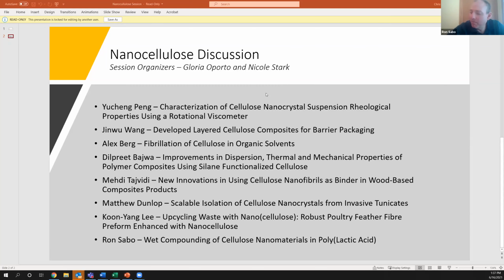You're on. So can you talk a little bit about the dewatering or press times and how these compare to traditional fiberboard processing, and maybe what you can do to improve that dewatering process? Yeah, the dewatering that we first started with was actually one-time dewatering. In one-time dewatering, we get to about 50% solids of our system. So on a dry basis, it's about 100% moisture content, as we wood scientists like to call it. If you press such a thing in a hot press, the press time is pretty long, about 45 minutes, which is much longer than what it should be for regular particle board. That's the main reason that we shifted from particle board into wet formed fiberboard and dry wall systems, where you don't do hot pressing. Instead, you dry the material in a large oven. That's the new direction that we are taking now.